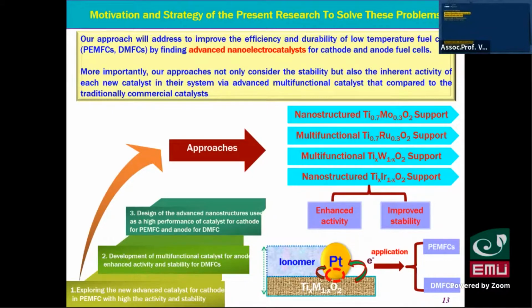So from our research, our approach is to change the carbon support. That means instead of the commercial catalyst using platinum on carbon support or platinum alloy on carbon support, in our system we replace the carbon support with a non-carbon support based nanostructure, doping a second metal into titanium oxide.